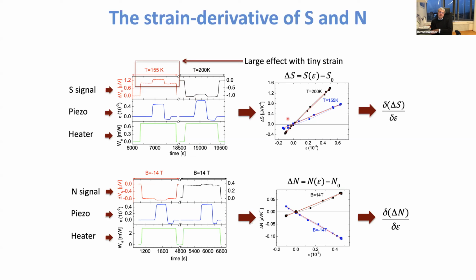What we then do is measuring these small effects as a function of strain plotted in this way. From the slope, we get then the change of the Seebeck effect as a function of strain. And the same you can even do for the Nernst effect, which is even a little bit more complicated because now you have to apply also magnetic fields, negative and positive ones, and you have to subtract the things. But also here, you can easily follow the change of the Nernst effect as a function of the strain. That by itself is already a real surprise because typically these effects are zero in usual metals, and now you can even measure their change as a function of these tiny strains.